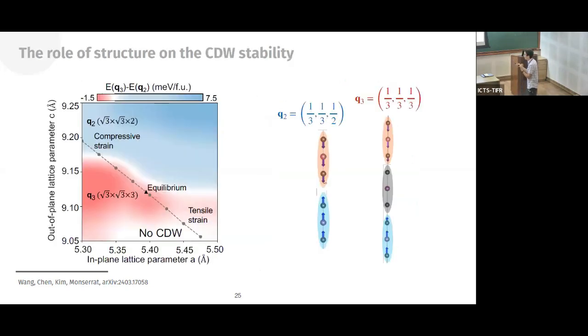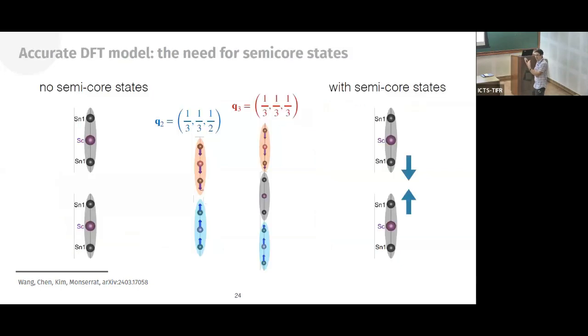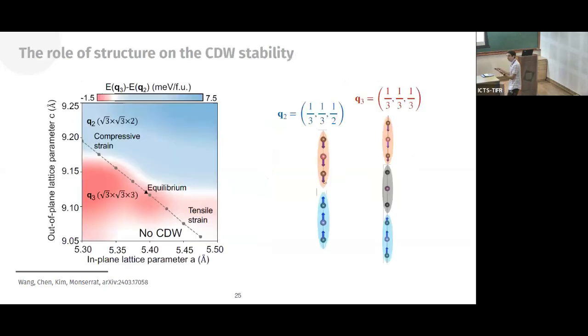But as you correctly say, in a sense that's a detail, and the reason why I highlight this is that that's what most people use to do the calculation, and that's why most people got this as the ground state. But in reality, what really controls the physics is the C lattice parameter, and there are other means by which you can change that. So van der Waals interactions would bind it further, so you would also go down this direction. If you use, say, a PBE functional, you would go the other direction. And that's also what other people have done. So that was just an example of the sort of changes that you can make to your system.